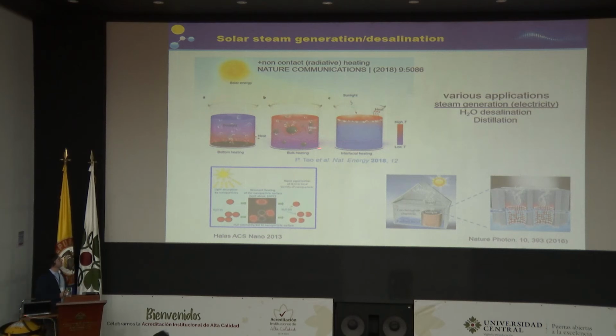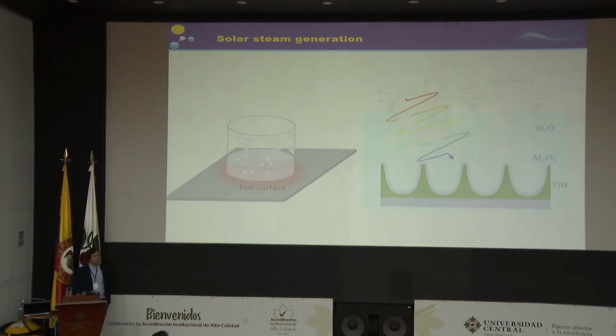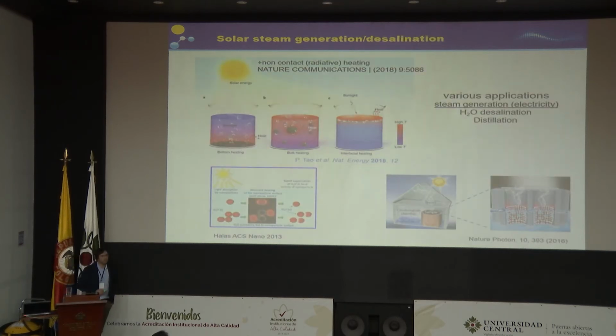Here we can see that this field really exploded in the last 3 years, and many different methods have been used, from nanoparticles to nanoparticles deposited inside membranes of alumina. Here they show, for example, that we can use a floating membrane, where inside we have plasmonic particles, and we can desalinate water in a very efficient way. This, of course, is very interesting for many different countries which have problems with fresh water.